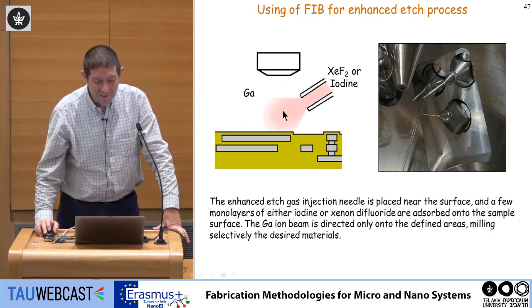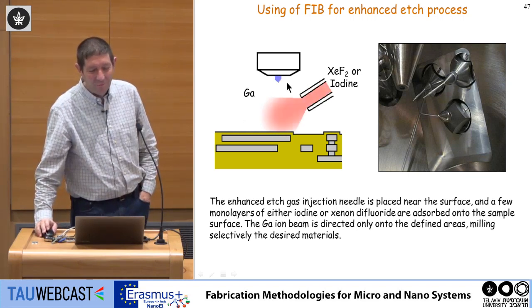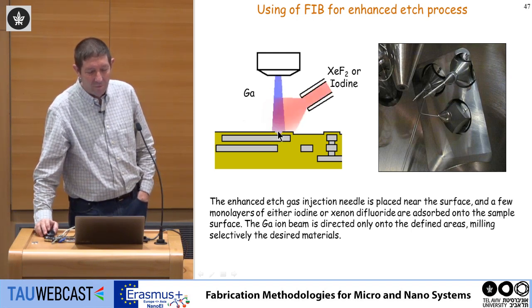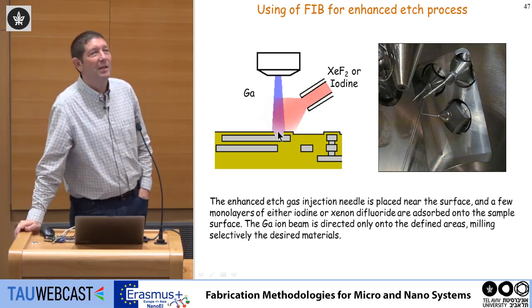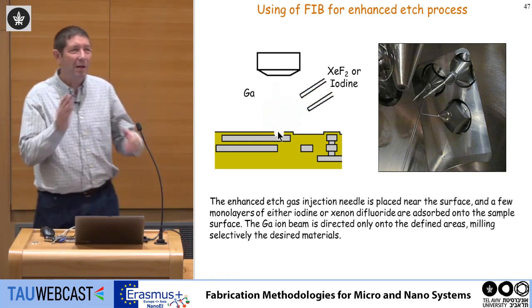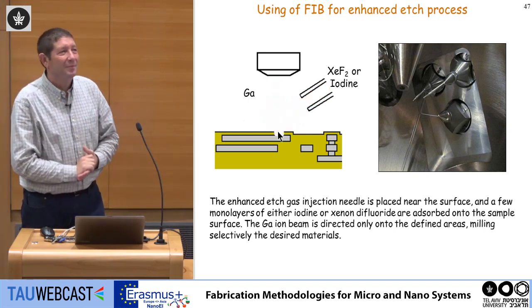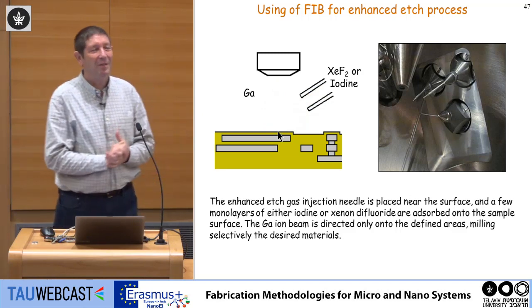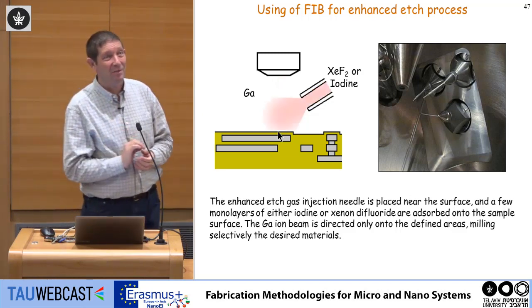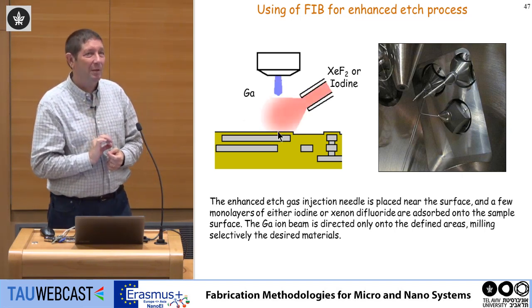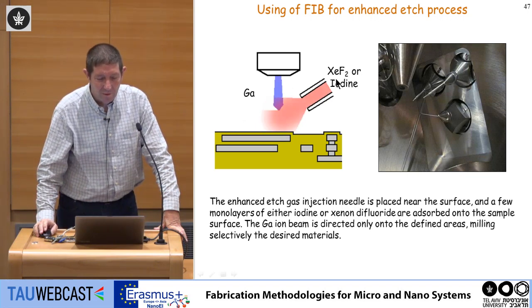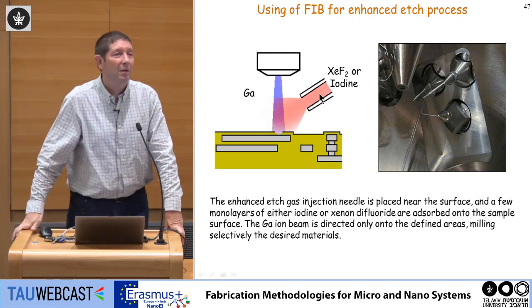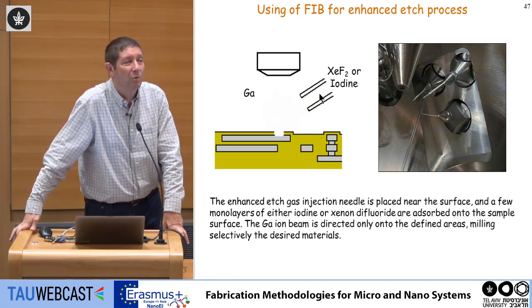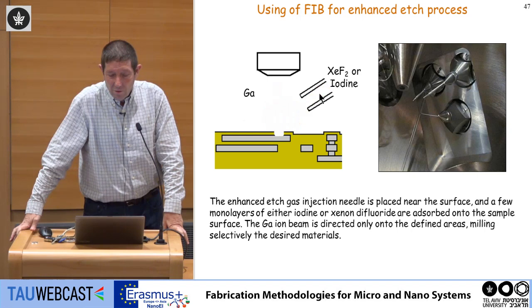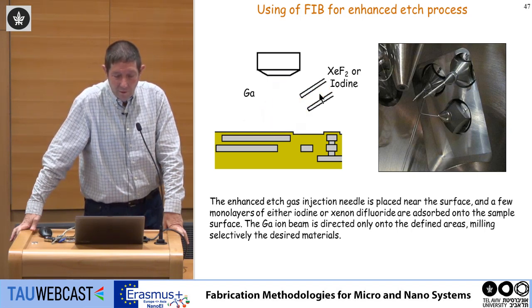Using the FIB for enhanced etch process. This is another thing that you can do. Let's say you want to etch this area, but you want to etch it gently. Now, one way is to do milling: you take the gallium ions and shoot them and break the material. Then you get sputtering. But let's say you want to have etching. Etching is more gentle because it's a chemical process. Now, xenon fluoride or xenon difluoride or iodine are very reactive gases, and they are used to etch silicon or polysilicon, or maybe aluminum.